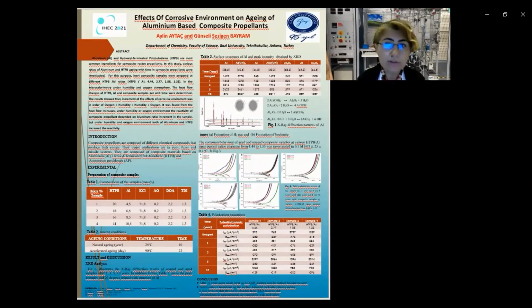The ratio of hydroxyl terminated polybutadiene and aluminum was changed, while the amounts of the other ingredients were constant. As you see in table 1, we used ammonium perchlorate as a solid filler, toluene diisocyanate, TDI, as a curing agent, dioctyl adipate as a plasticizer, and some antioxidant like AO. All samples were cured at 60 degrees centigrade for a week. Yes, you can see table 2. And we used the Arrhenius equation. The Arrhenius equation has been used to predict the behavior of the materials in shortened times with accelerated aging instead of natural aging for a long time.